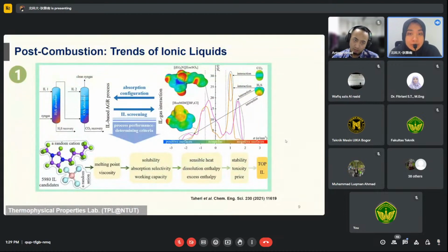So first, before we do the experiment, actually we did the prediction. So we use here COSMO. Later I will give a brief description about COSMO. COSMO is a kind of modeling that we use to predict the interaction or the surface profile interaction between the CO2 or acid gas with the ionic liquids. So why do we need to predict first? Because we would like to check whether this ionic liquid has possible high interaction or not with our compound. So we don't do trial and error, but we try to predict first according to the molecular structure.